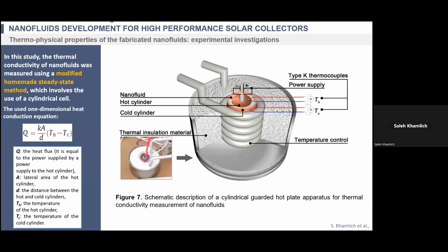Now, having made these nanofluids, we really have to test them to find out if the copper nanoparticles contributed to enhancing the thermal conductivity of the ethylene glycol, because ethylene glycol is a heat transfer fluid, of course. So we designed this system. It's called a guarded hot plate, a modified, cylindrical one. It has a cylinder, which we call the hot plate or hot cylinder, which is the inner cylinder. And it has the other cylinder there, which is the cold one. This is the hot and the cold one.